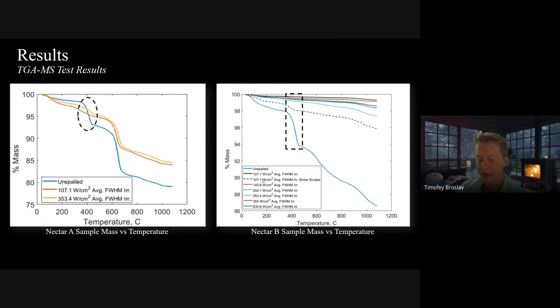Shown here is follow-up testing using a TGA-MS test setup to showcase the differences between unspalled and spalled samples of Nectar A and Nectar B. Both Nectars actually show that they lost water around the 400-degree mark, and this is due to some talc dehydroxylation, so talc lost water. So both show that they actually did produce water from this mining method.